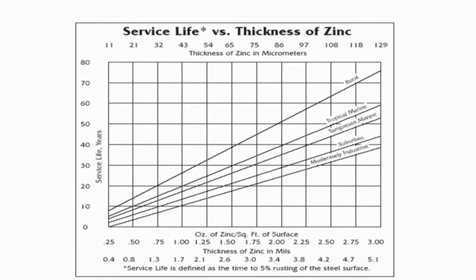This is because of the biggest advantage of having a completely dense, pore free coating and a very strong interface, and also a very thick deposited layer. Now, if you talk about the zinc coating thickness which is desired, because of the application requirement, or the requirement of service in a corrosive environment, the thicker the coating, the better the service life. Service life changes from 5 years to as high as 80 years depending on the thickness.